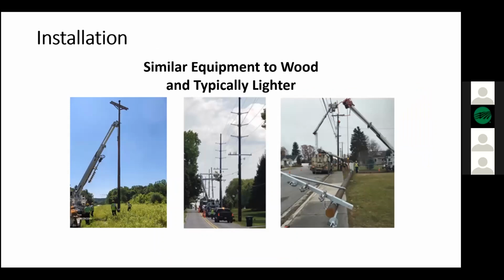Installation. It's much like the wood poles that many of your crews install today. Very similar equipment. Not much difference. I guess the only thing that comes to mind is, instead of having a chain when you're hoisting up or lifting these poles, we recommend maybe a nylon sling, just so you don't scratch up and scuff up the pole as much. But very, very similar to equipment used today. And actually, ductile iron poles, by comparison, are lighter than the wood poles by 25–30%, depending on the class and the height of the pole.